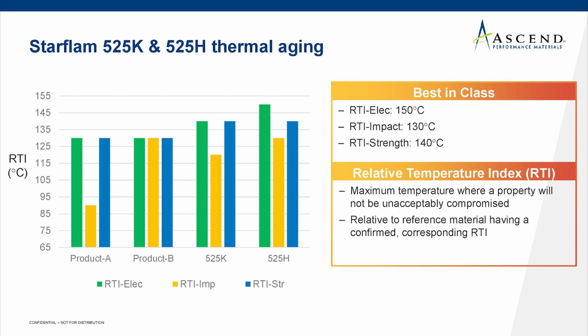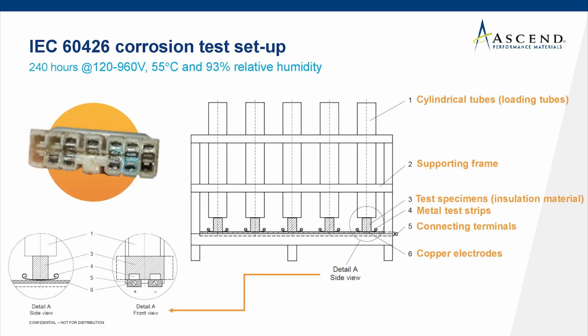Metal contact corrosion is also an important characteristic, and you can see a corroded connector there on the left. The test that we do is an IEC method, and it's for 10 days at a given selected voltage, so you can only run one voltage at a time, and it's done at 55 degrees and 93% relative humidity. In the diagram there, you can see that we can test 5 samples at a time, and there are cylindrical tubes that are holding the polyamide compounded plates.